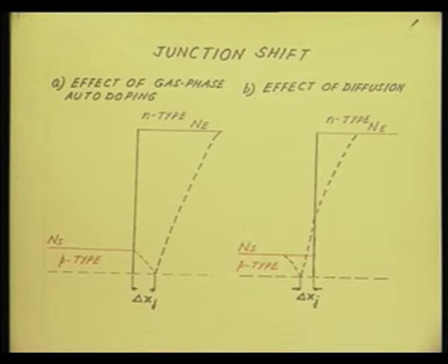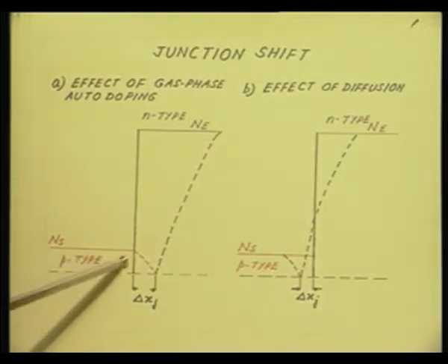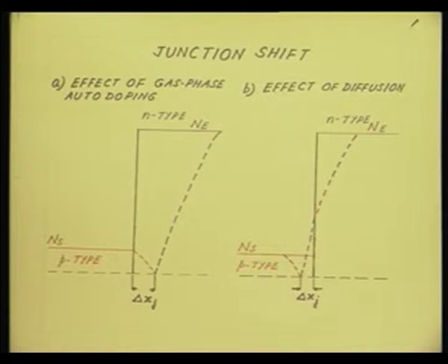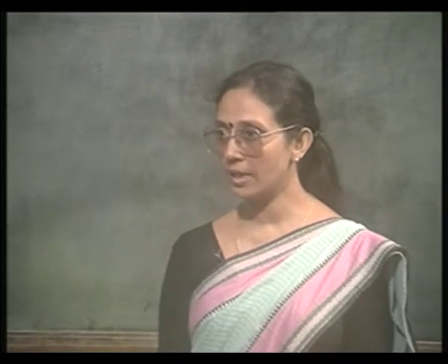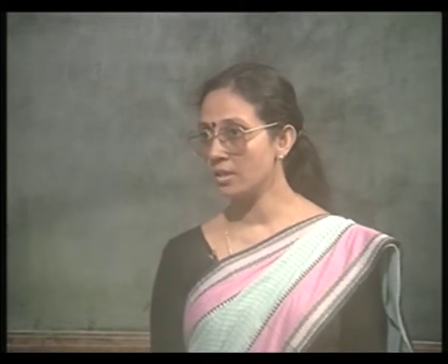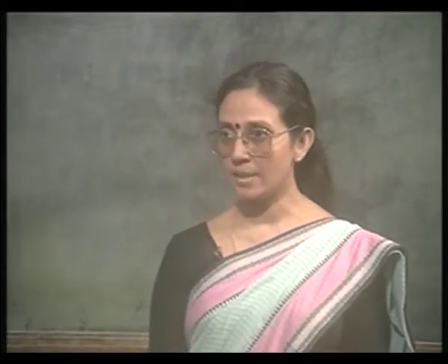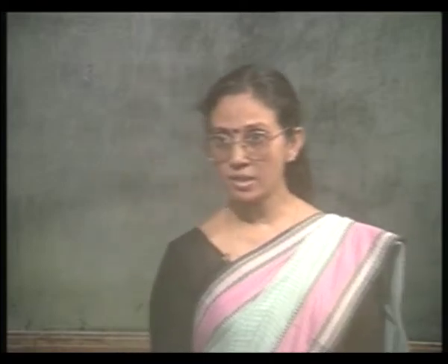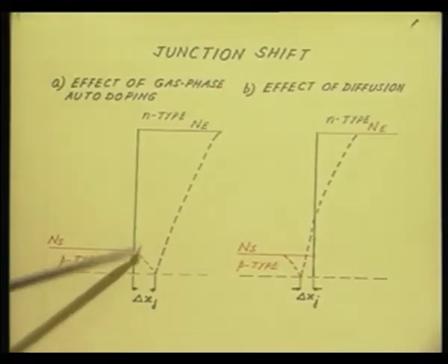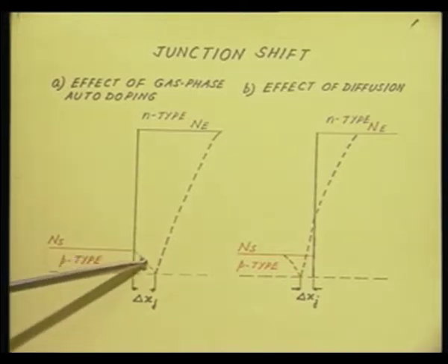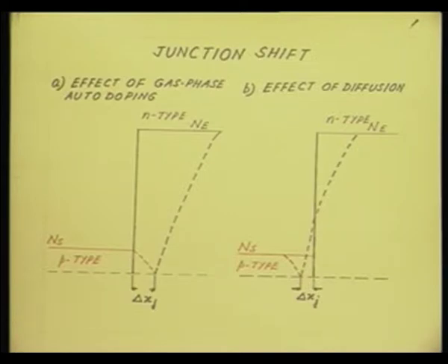That is the first figure. If you look at that, this is the effect of gas phase auto-doping. Let us look at this. What is happening? I have the substrate with a doping concentration Ns. It is a p-type substrate. Gas phase auto-doping is that effect, that is before the epitaxial layer growth, when the substrate is being heat treated, some of this p-type dopant will escape, it will evaporate and it will modulate the gas stream. Okay. So, this is what is happening, some of the p-type layer is escaping and getting reintroduced into the epitaxial region.